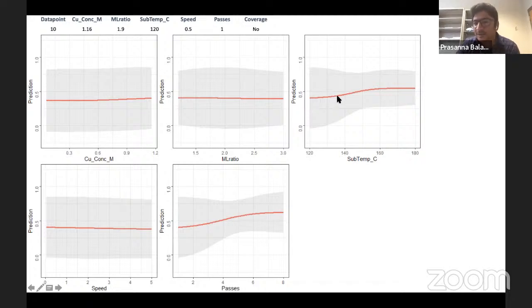But then look at this plot, right? What this plot says is that if I keep everything else constant, the concentration of the solution, the speed at which the blade is moving, the number of passes, and so on, and I change the temperature alone, if I crank it up beyond 150, then the probability goes from less than 0.5 to slightly above 0.5, right? Indicating that likely this can form a fully covered film if you do this particular step. In fact, our colleagues went and ran this experiment, I believe, at about 180 degrees, and we were indeed able to get a fully covered film as a result of this visualization through the explainable AI approach, right?